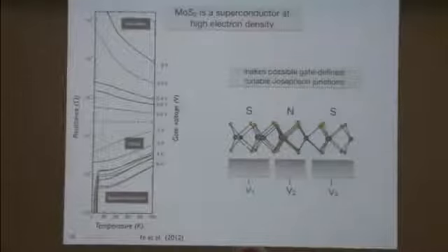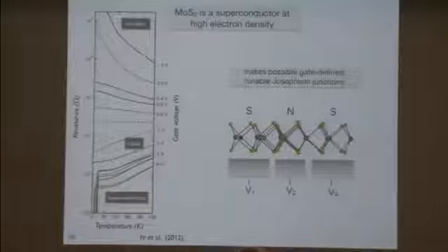Finally, another topic that we're interested in looking at is investigating some of the quite surprising superconducting properties of these materials that were discovered by Yoshihiro Iwasa's group last year. When I showed you the transistor data before, we were able to change it from a metallic conductor in the on state to an insulator in the off state by changing a gate voltage. Here, by going to even higher gate voltages and higher electron densities, they're able to go from insulator to metal all the way to a superconducting state when the temperature was cooled below 10 Kelvin, which means that you can access this entire range of properties of the material simply by changing a gate voltage.